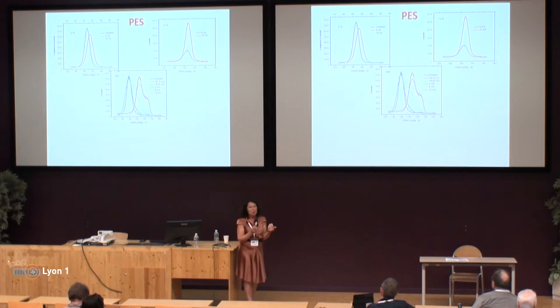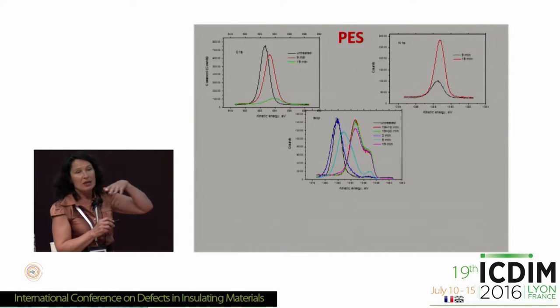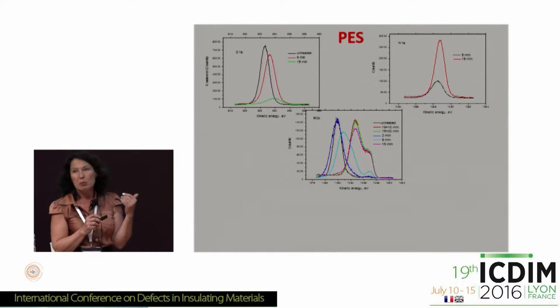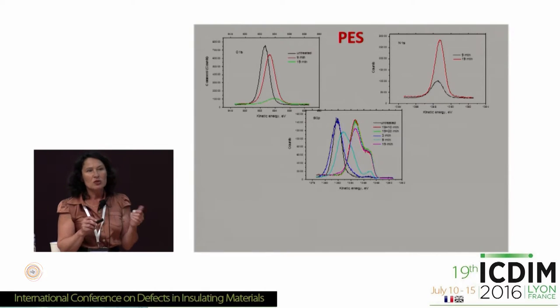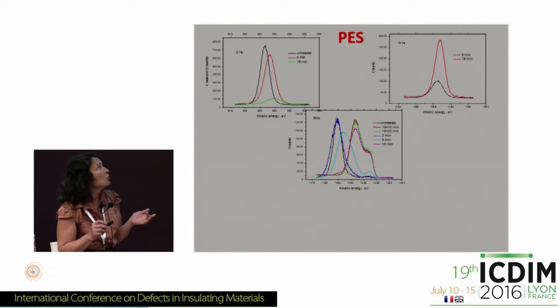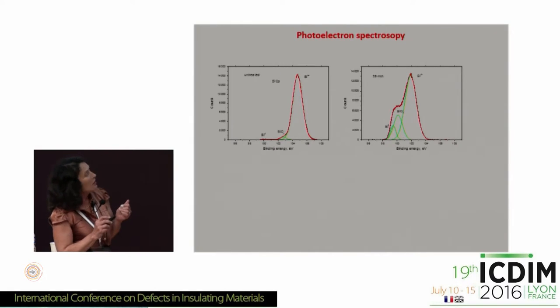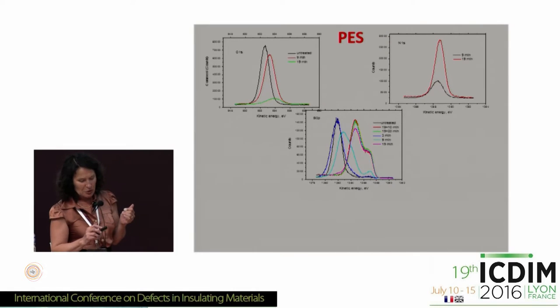Since all the samples were covered with a 10 nanometer layer of silicon dioxide, if you do not treat the samples, you see just the silicon dioxide, since the escape length of electrons with energy of about 1 keV is about 10 nanometers. To look inside our structures, we have to remove this layer, and for that purpose argon etching — bombardment of the surface by argon ions — was applied. The experiment was done at Kurchatov Institute, where the setup is quite new, so calibration of the regimes, modes, currents, and focusing was needed.